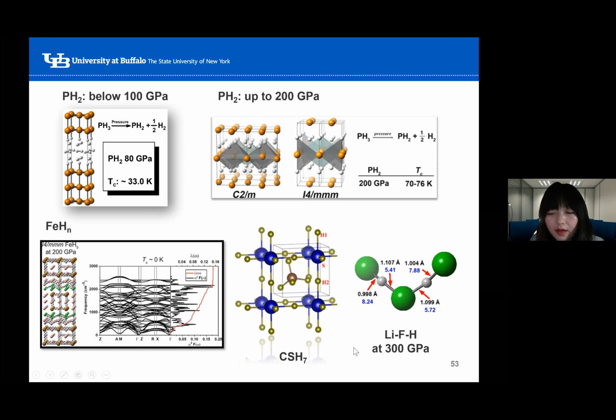systems, CSH7 and lithium fluoride hydrogen. We found a good candidate for superconductivity in CSH7, and found a unique structural motif in the lithium fluoride hydrogen system.